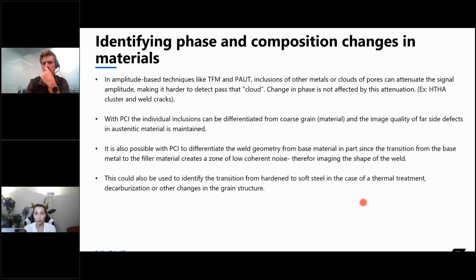And this could also be identifying the transition from hardened to soft steel. Sometimes if it's heat treated, there can also be decarburization when it's in service for a while, or other changes in that grain structure. Sometimes the PCI will pick it up because it's very sensitive to those very small changes in the phase and the frequency.